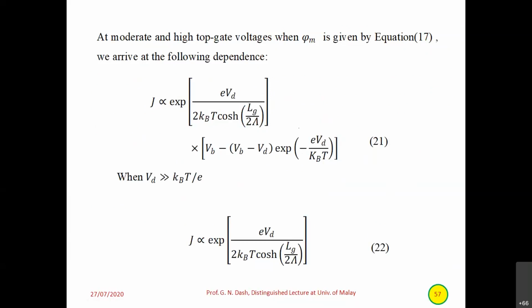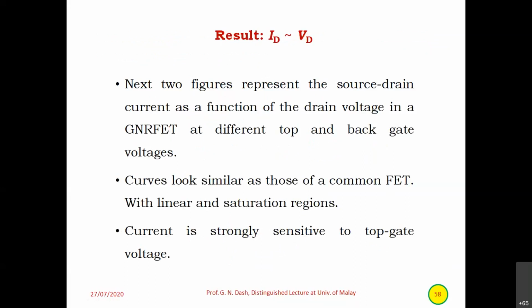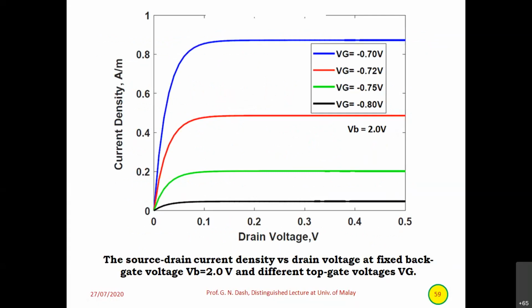So similarly, this is J proportional to this, is proportional to this, and the result is the same. These two figures represent the source. You can see the result: drain voltage versus current density for different values of the gate voltage. Initially for low VD, the current increases almost linearly. But when VD exceeds 0.1 volt, the current saturates and becomes constant.